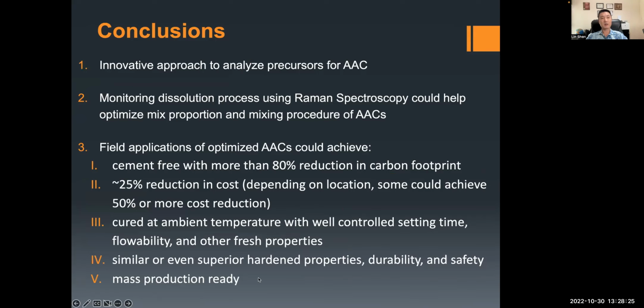So in conclusion, we have some innovative approaches to analyze precursors for AAC. We also monitor the dissolution process using Raman spectroscopy, which could greatly help us optimize the concrete mix proportions and the mixing procedure for AAC. The field application of optimized AAC could achieve cement-free concrete with more than 80% reduction in carbon footprint and around 25 to 50% reduction in cost. The concrete can be cured at room temperature with very well controlled setting time, flowability, and other fresh properties. It has similar or even better hardened properties, durability, and safety. And we think in many cases, it is mass production ready.